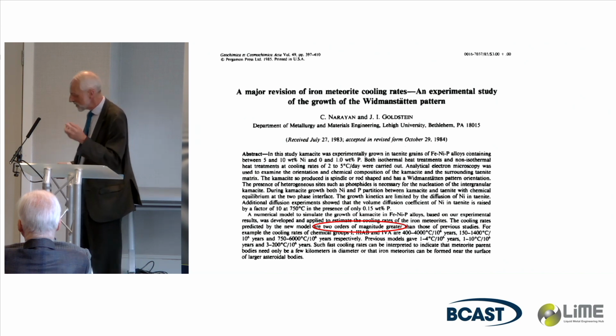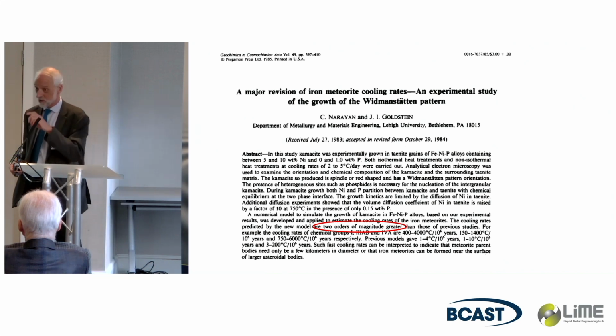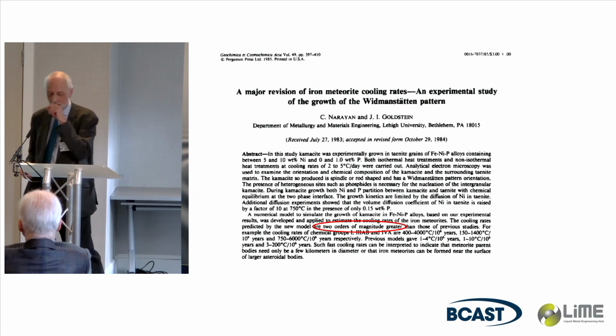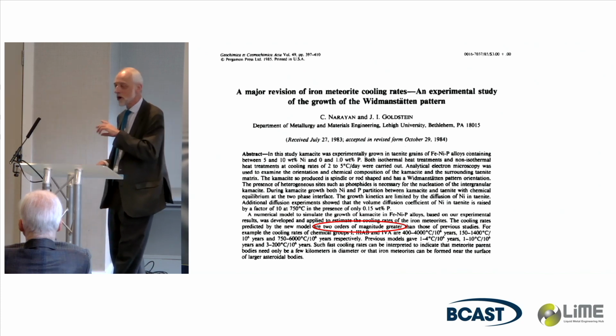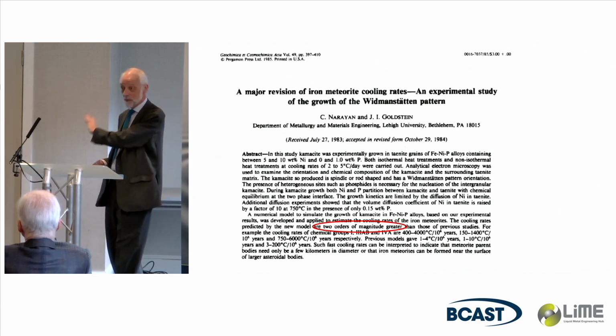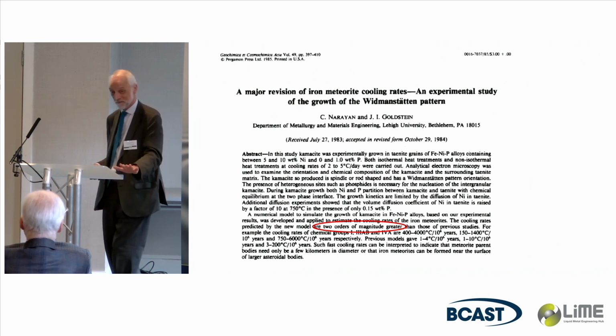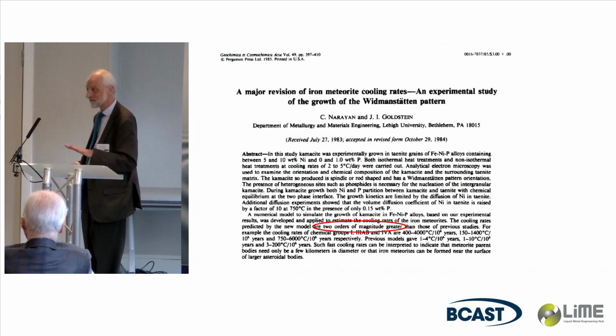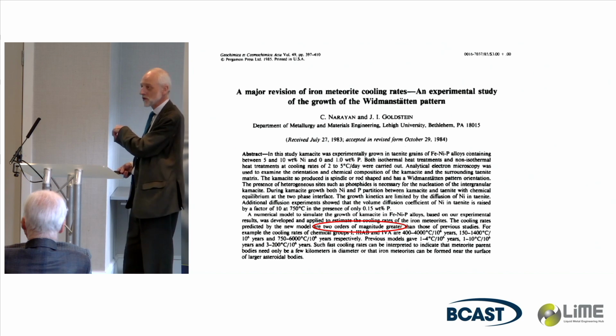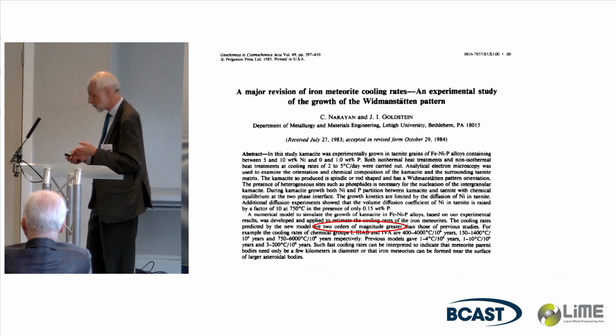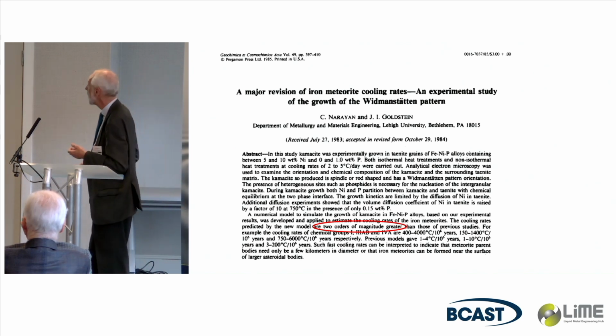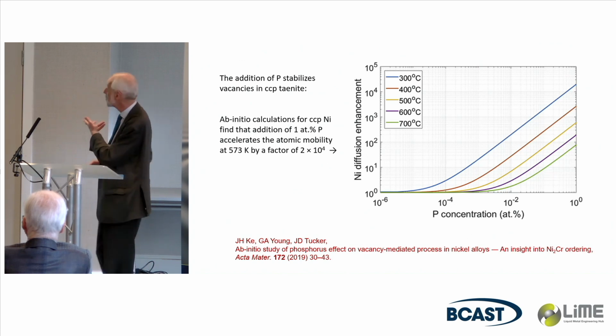their earlier estimates of meteorite cooling rates, which of course is degrees over millions of years, were wrong. And they were wrong because the lab experiments they'd done to simulate meteorites didn't put phosphorus in. They just looked at the iron and the nickel. And when you do put phosphorus in, it accelerates the diffusion, presumably by stabilizing vacancies. Now, that was just a 2 order of magnitude shift.